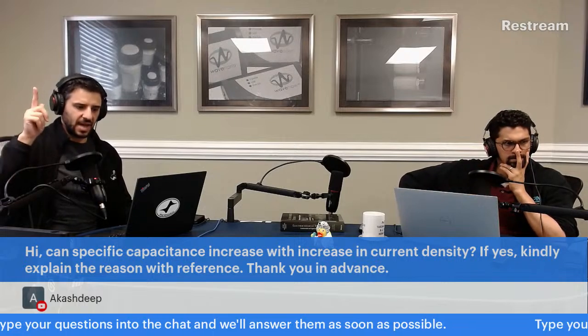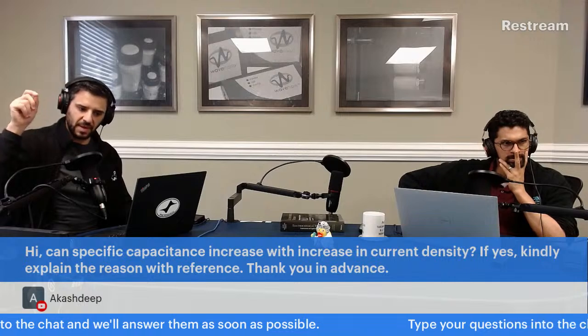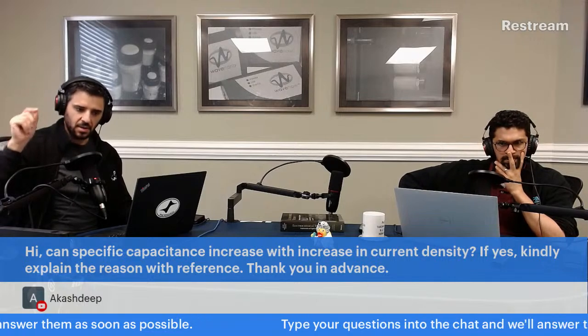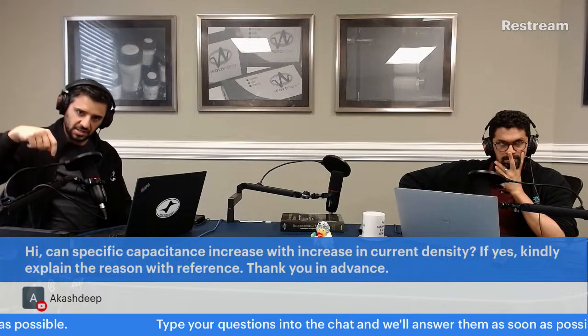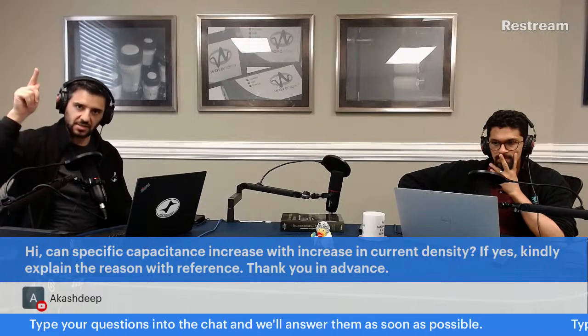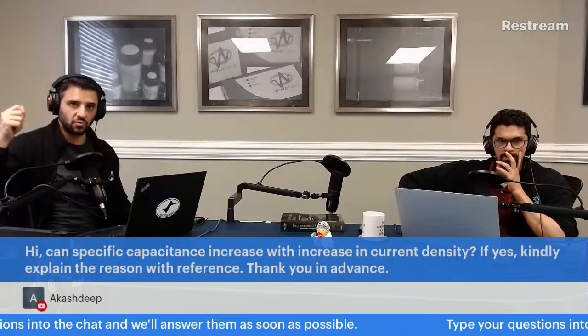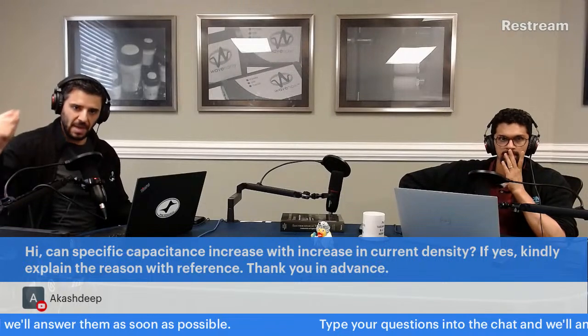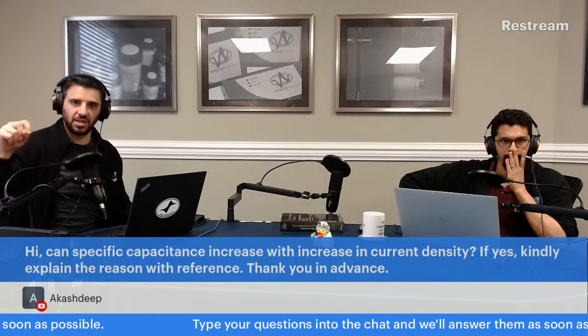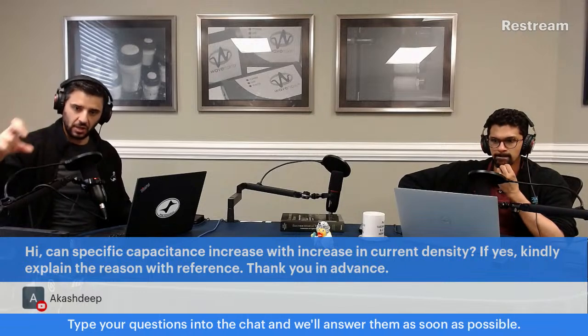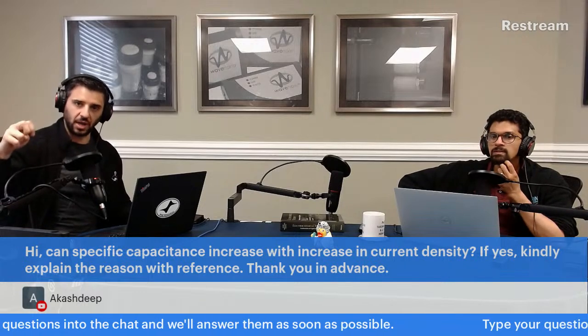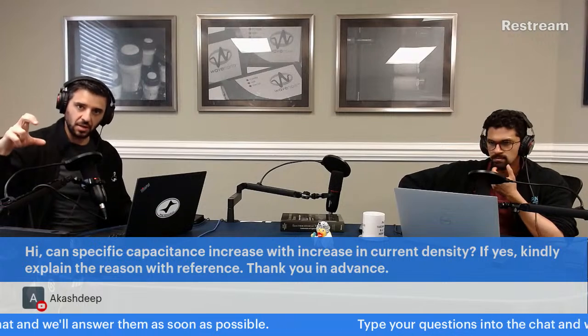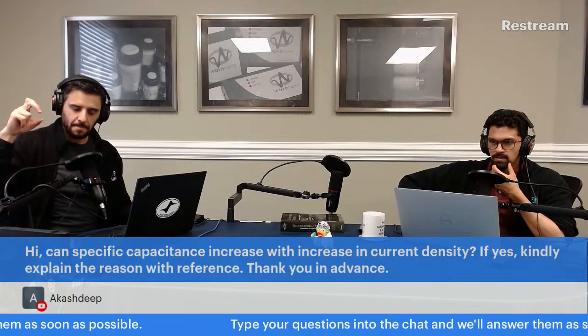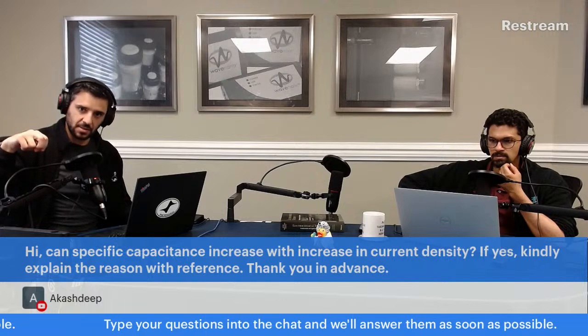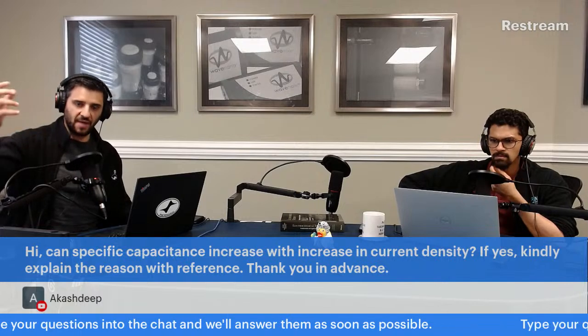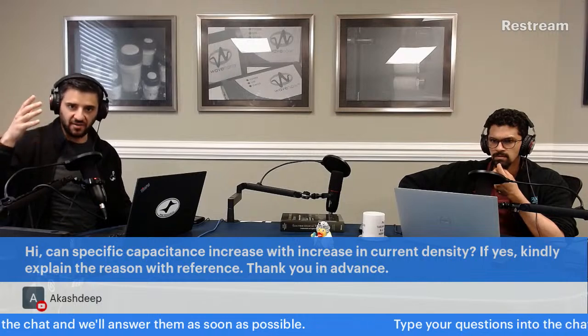You're increasing the mass, which means specific capacity goes down, capacitance goes down, but you're decreasing the surface area, which means the current density goes up, right? They're going in opposite directions. And the reason for that is that as you increase the mass, it's like adding more material. You're loading your working electrode with more and more material. Often that means the area does decrease because you have agglomeration of material.